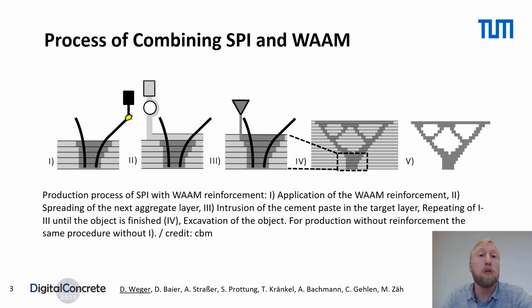Why we need the space between the welding spot and the particle bed, I will explain in the next slides. In the third step, cement paste is applied to bind those areas where the specimen shall be produced. Then the steps of application of the next layer of steel, aggregates and cement paste are repeated until the structure is finished. In the last step, the structure becomes excavated. This method allows the production of more complex structures than is possible with extrusion techniques due to the supporting ability of the surrounding non-bound particles.